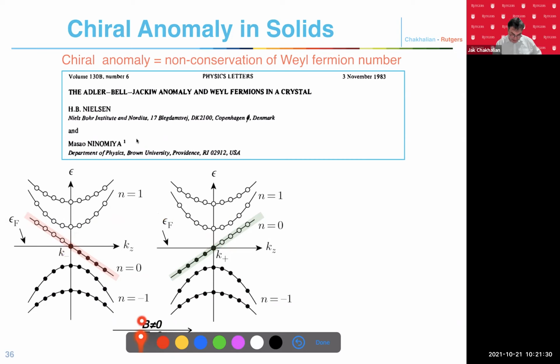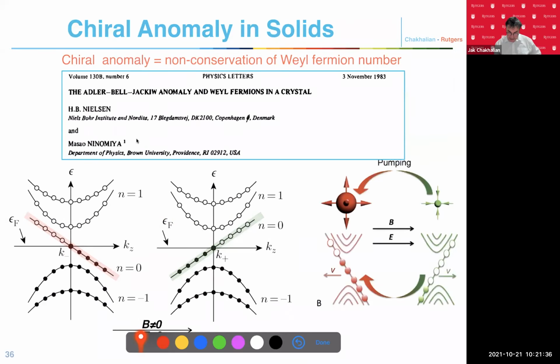And then what they say, okay, so this is what magnetic field does. It produces this kind of Landau levels. And then you apply electric field. And then with this electric field, of course, electrons move against the electric field and they start moving this way. But that means, in turn, that you're moving electrons with the chirality of those Weyl fermions. They have chirality +1 and chirality -1. And that's what's called the non-conservation of Weyl fermion number, because here the chirality is changing and you're pumping electrons with this chirality into electrons with that chirality. It's a very, very strange thing, right?